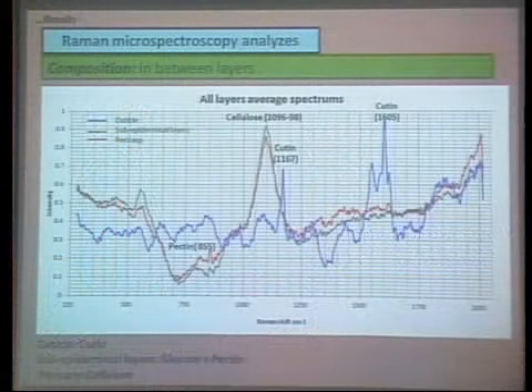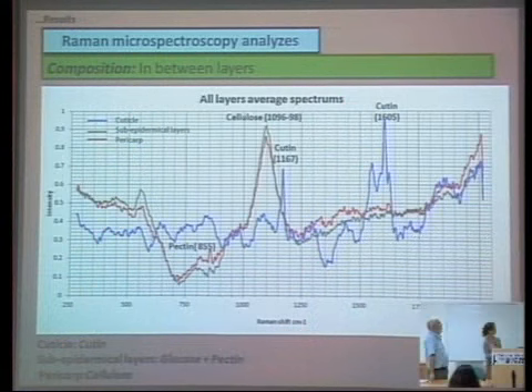What do you mean by concentration? I don't want to call it concentration because it's not an exact measure of concentration, but it's a measure of intensity. All right, but you did show some difference in intensity, at least in the cuticle, isn't it? No, it's different components for each one of them. You see this one here? The blue one represents the cuticle, and it only has cutin. The second one is the subepidermical layer, the red one, and it has pectin and cellulose. And then the pericarp only has cellulose.